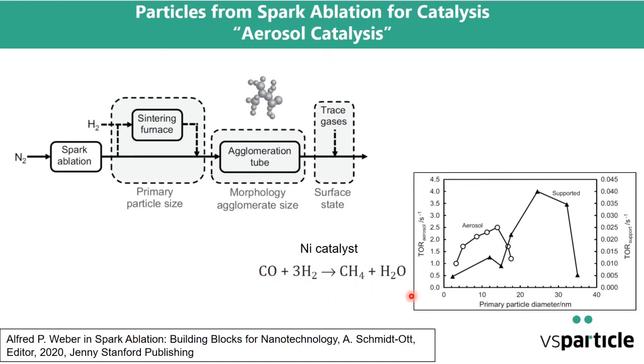In this case, they used a nickel catalyst, and they found that the turnover rate as a function of the particle size is such that in the aerosol phase, the best particle size is around 14 nanometers. And in the supported case, they did both. They also supported them on a substrate. The optimum size is larger. So this is a screening method, in this case used only for the particle size within the agglomerates.